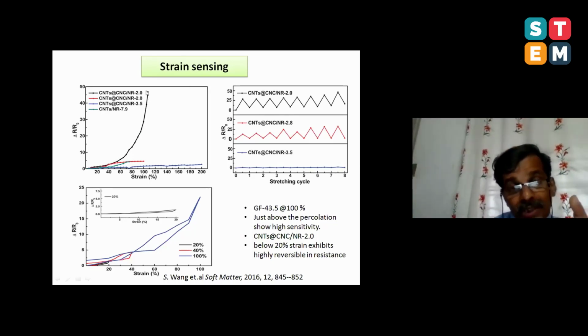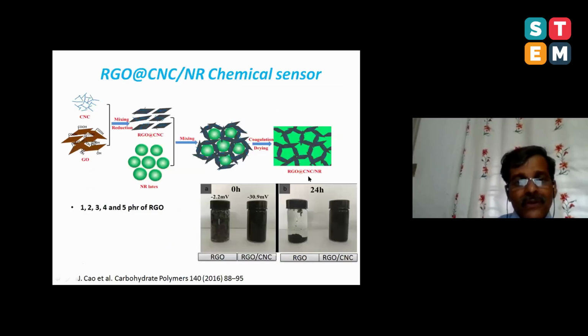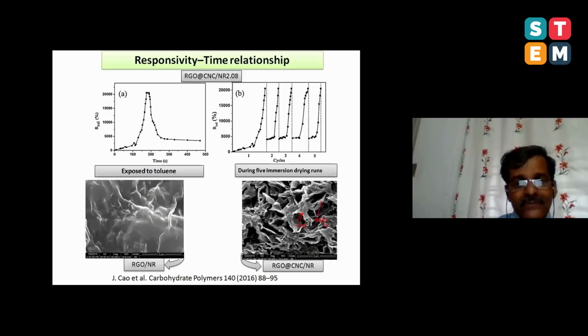If you combine nanocellulose and CNT together, you get sensitivity. If you use just CNT alone, you don't get any sensitivity. So this is again a very nice way of making good sensors. Look at the variation of the resistivity as a function of stretching cycle. I will skip the slide.